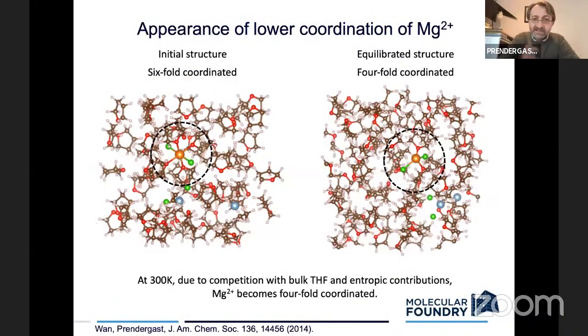So we did the thing I said you shouldn't do. We just threw stuff into a box and modeled it initially. This was back in 2014 as well. And one thing we noticed was that the intuition you might have from these cluster calculations, where you start with something that looks like a 6-fold coordination, magnesium here, 2 chlorines, and 1, 2, 3, 4 surrounding molecules of solvent, ended up equilibrating, in quotes, to some structure that was at reduced coordination, 4-fold coordination, with the 2 chlorines on the same side, amazingly. You think electrostatically, why would they want to do that? They repel each other. And then only 2 solvent molecules involved.